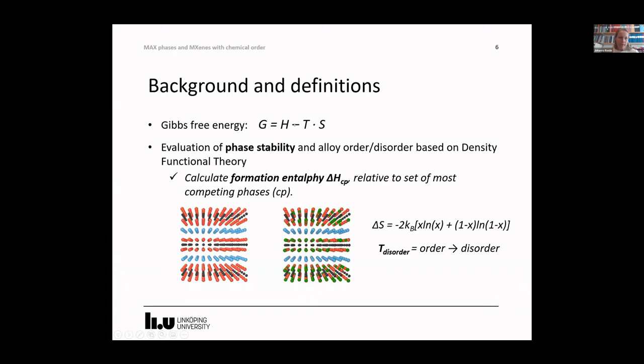But if we focus on the enthalpy, we assume that the temperature is 0, and for pure ternaries, 0 Kelvin calculations are actually quite useful. But if we investigate alloys, here you see an M element alloy, the effect of temperature becomes important. Not so much for vibrations, but for the contribution of entropy or disorder to Gibbs free energy. The entropy is defined based on this expression, where x is the alloy concentration on the sublattice that is alloyed. And by calculating the formation enthalpy of an alloy, and by including the entropy, we can actually estimate at what temperature we go from ordering at lower temperatures to disorder at higher temperatures.